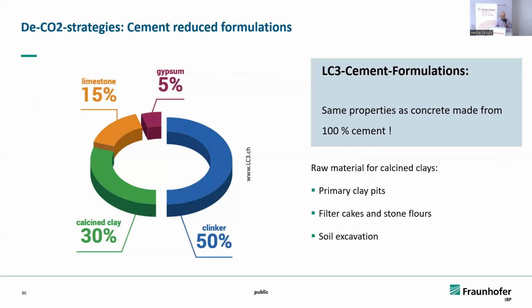Coming to a material Lucas and Carolin mentioned, cement is mixed with so-called supplementary cementitious materials. In Germany, usually we use fly ash or blast furnace slag. But the problem is in 2030, when the coal power plants will shut down, we have a lack of fly ash. So we will miss 2 million tons of fly ash.